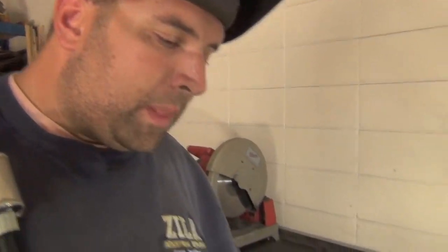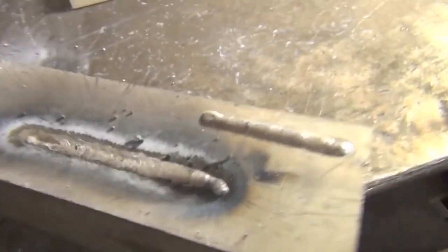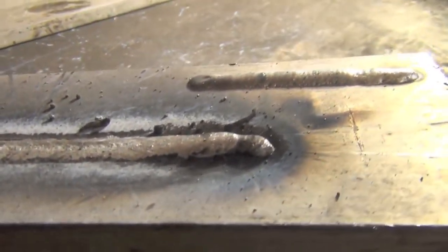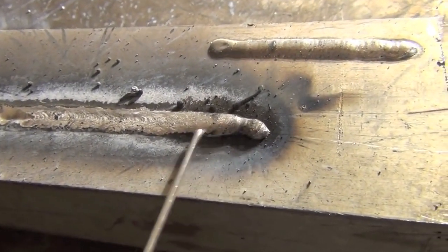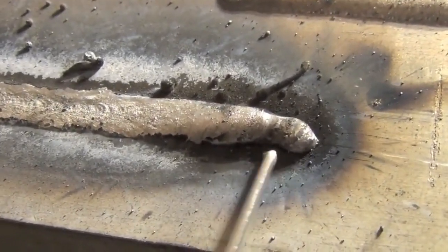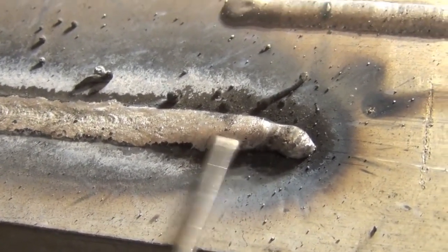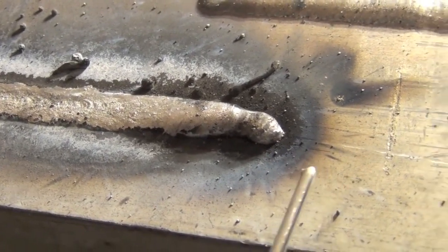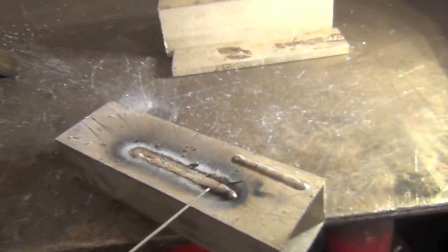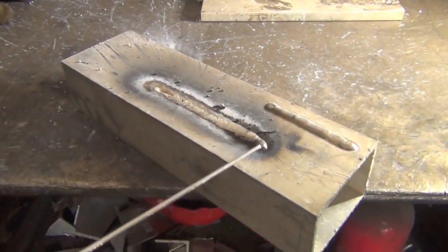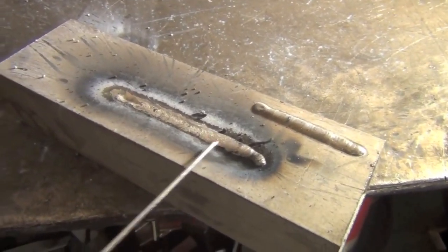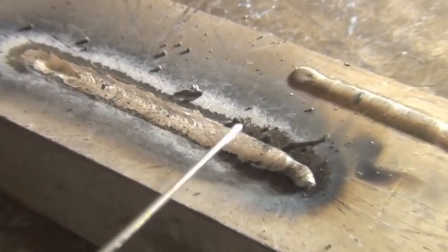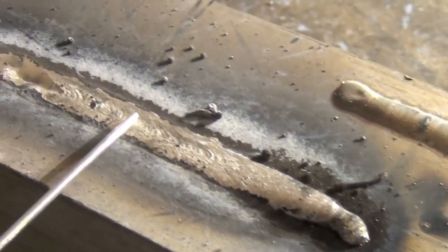So that is the weld we just did, and it shows some spool gun or aluminum MIG specific characteristics. First of all, you see the first inch here is kind of cold, sitting on top of it. What happens there is the material is not preheated to temperature. If you preheat the material, then this is eliminated. As soon as the material gets saturated with heat from welding, you have a nice clean bead.